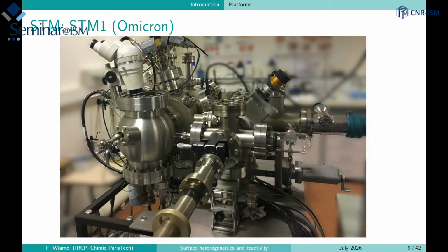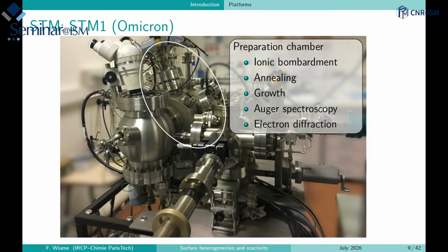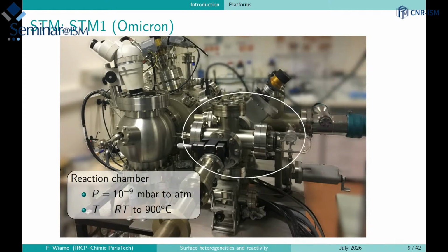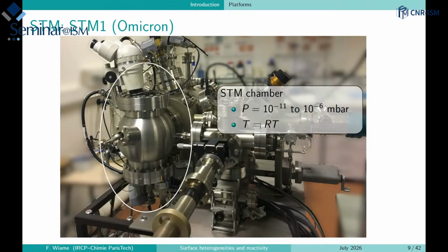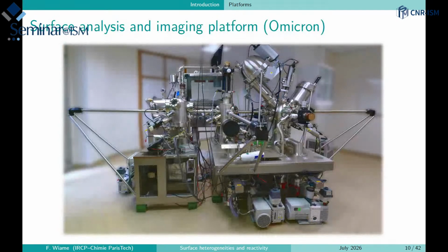So this is an STM at room temperature with, again, a preparation chamber for preparation, growth, with Auger and LEED measurements. Then we have a reaction chamber where we can expose the sample to gases from 10 to the -9 to atmospheric pressure, from room temperature to 900 degrees Celsius to grow some layer on the surface. And we can also do the same, obviously at lower pressure, but we can also do the exposure while we are doing the scanning tunneling microscopy measurement. So we can follow in real time the reaction at the surface at room temperature, but at least in a range that enables us to follow this.